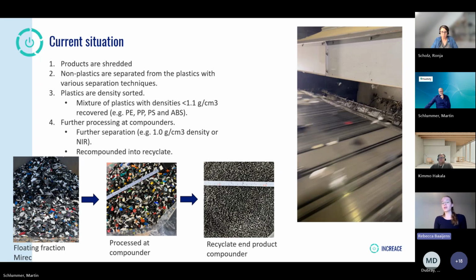So after this, we then go to the density step at 1.1, which then results in the fractions you see in the bottom. So going from our floating fraction, which has PE, PP, PS, and ABS, the compounder then processes it further, separating it usually at the 1.0 density step to get the polyolefins and the polystyrenics separate, and sometimes further steps with near-infrared sorting. And once they have completed their separation, you get a smaller step as it is processed by them. And then at the compounder as well, they indeed, as Martin explained, make the new recyclate that can be used by the producers of products. So if you could go to the next slide.